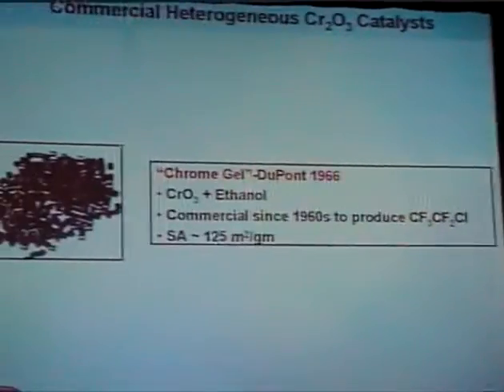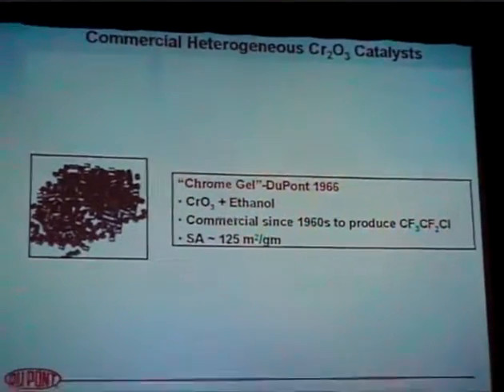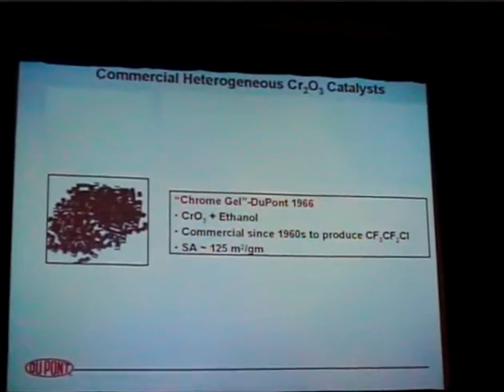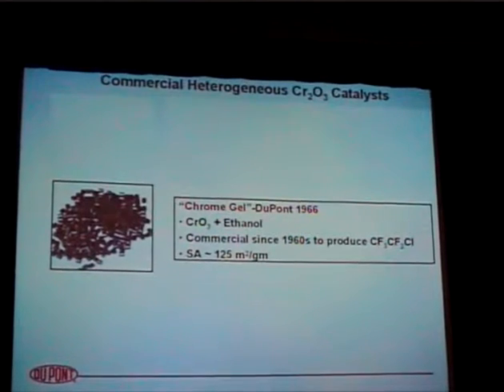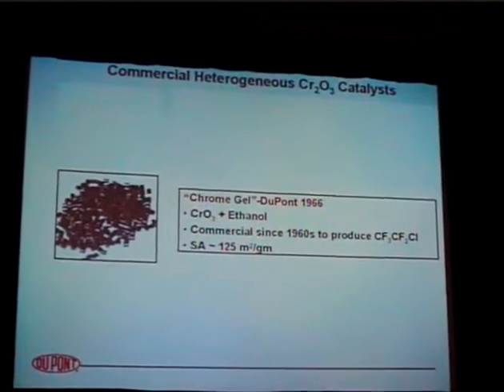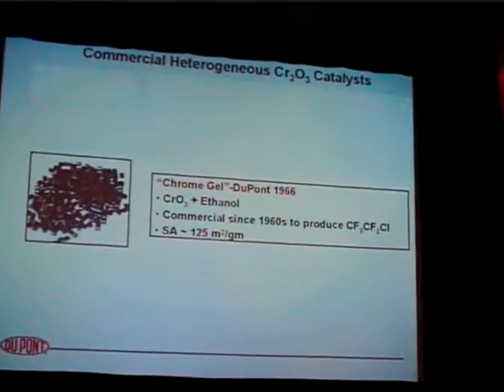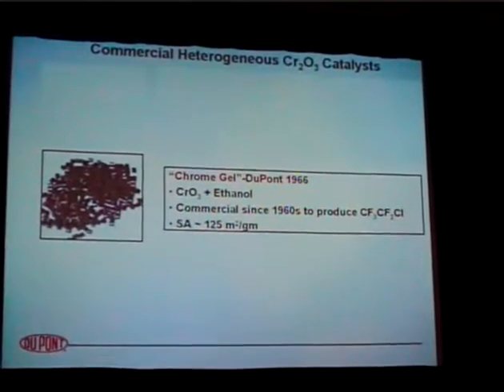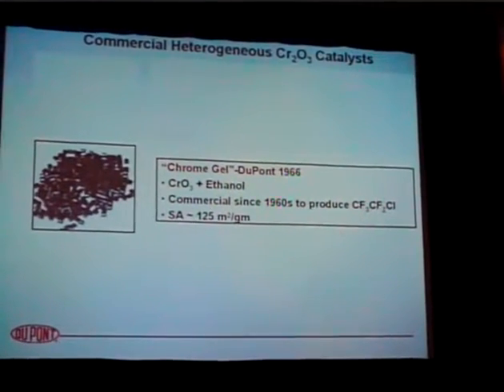Another way to make an active and a very, very good catalyst is to reduce chromium-6 with ethanol. That gives another version of chromium oxide, chromium-3 oxide, and that's been used by DuPont since 1960 as well to make the more fluorinated materials like chloropentafluoroethane, CFC-115. It has fairly high surface area. But the best catalyst that we have found in all of the work we've done over